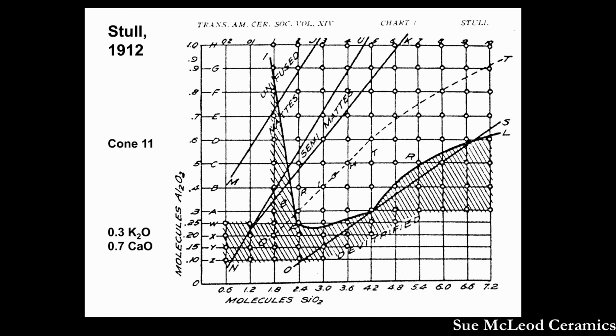So, what does Stull's map tell us? Stull discovered that with a consistent flux ratio, a glaze's surface quality, whether it's glossy, matte, crazed, or underfired, is determined by the glaze's silica and alumina levels and their proportion to each other. Stull predicts that glazes will be matte when the ratio of silica to alumina is 5:1 or below. As the silica to alumina ratio increases, the glaze becomes glossy.